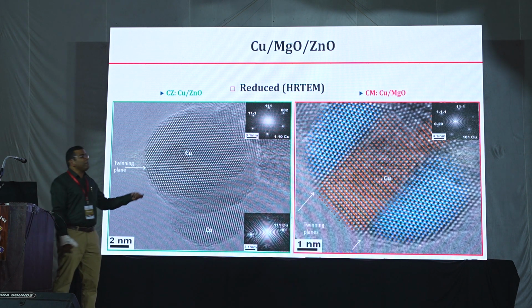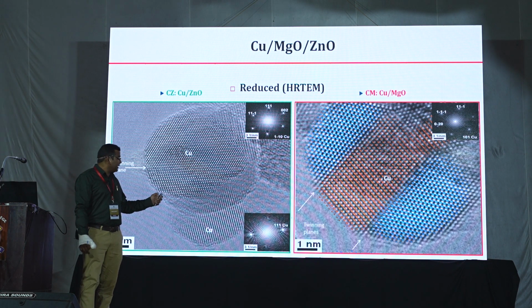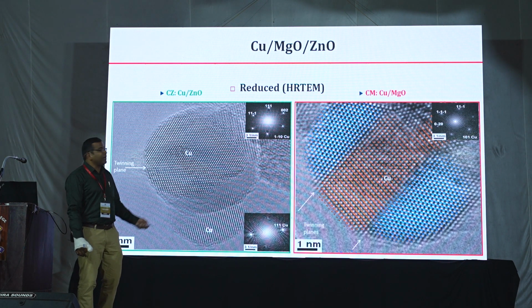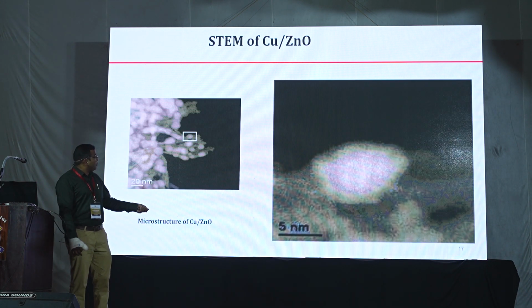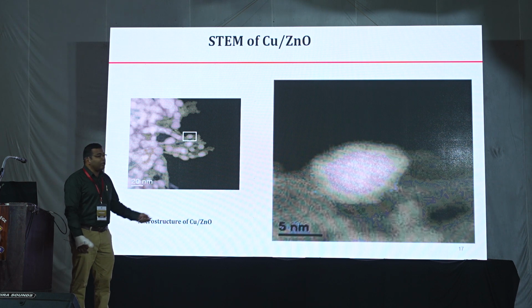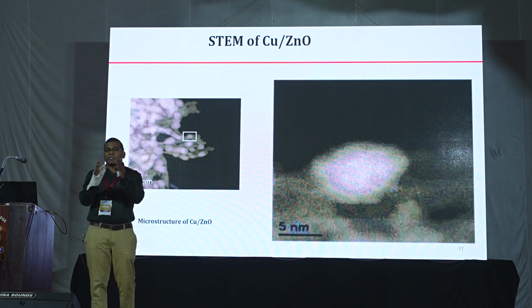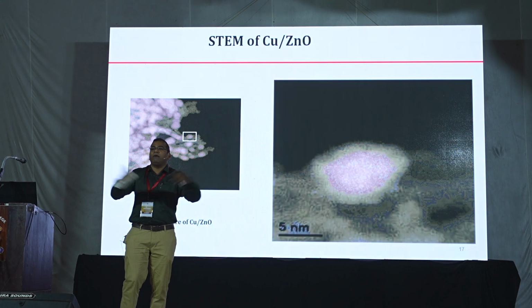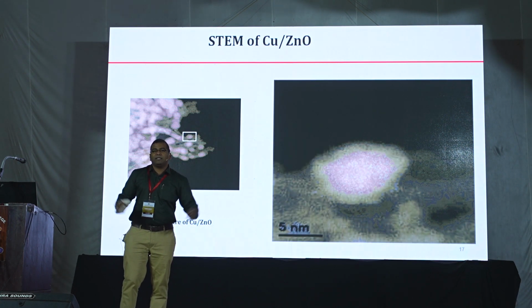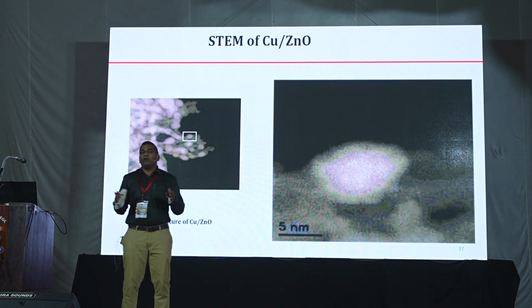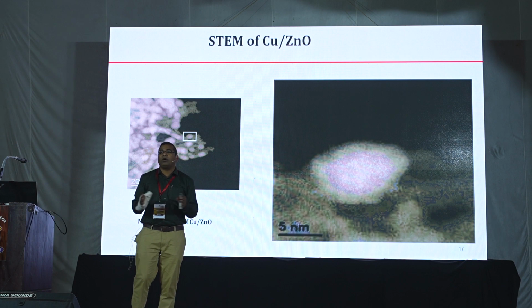Okay. Then these images you have seen are very nice images. You see this is 1 nanometer, and you see so many planes and other things. So I'll quickly go. You see this one, this is a copper particle. You see how it's nicely covered and protected. If you expose the copper nanoparticle as such, all the particles will agglomerate, and in 1 minute you will lose the activity. But if you can keep it in this way, these catalysts are quite stable. You won't believe it, it will be stable for more than 2 years in the industry reactor.